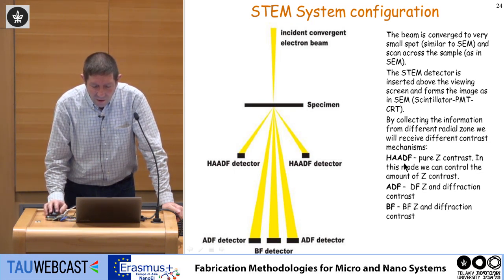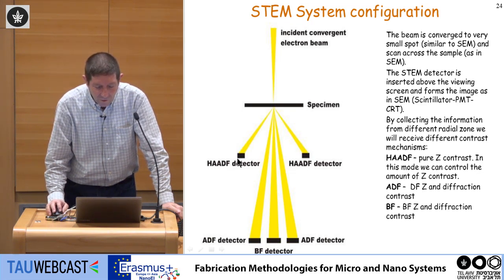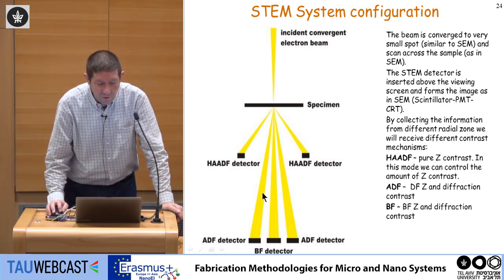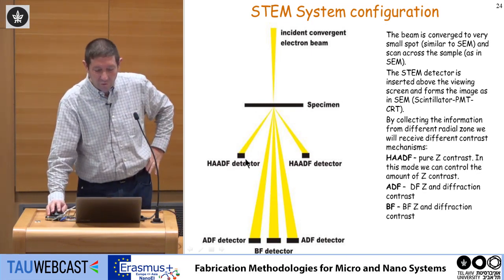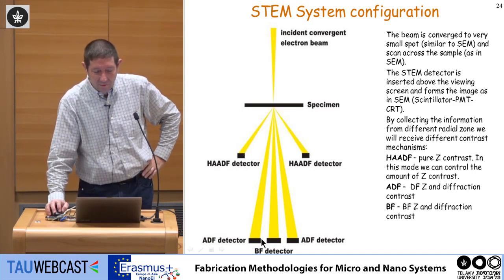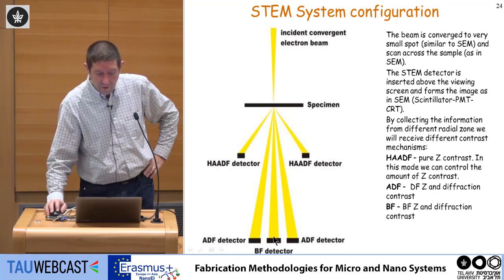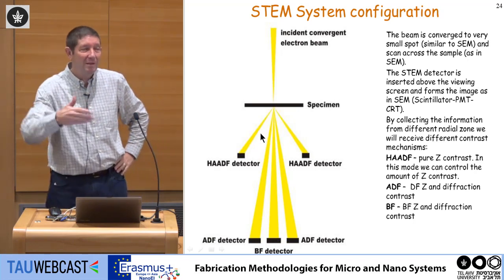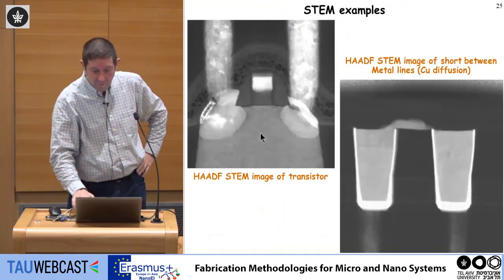So we have the HAADF, this is the dark field, this is called dark field. So we can collect the high angle diffraction, the lower angle diffraction. This is called bright field, the center beam. If you think about this diffraction, this is the 0 order, 1st order, 2nd order of diffraction. So you can collect various orders of diffraction. This is the high angle, the regular, or the bright field, and you can synthesize an image out of this information.